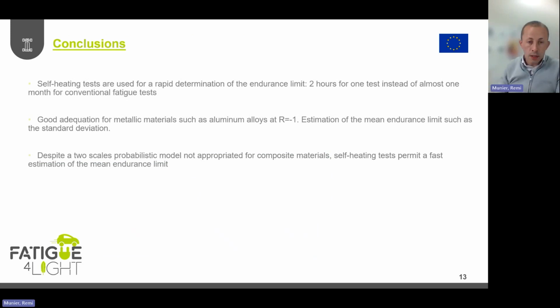And then to conclude, here we can say that self-heating was used for the rapid determination of the endurance limit. One of the biggest advantages of the method is the reduced time in comparison with conventional fatigue tests. As I said before, there can be some mistakes and some limitations, but for bare materials with a homogeneous volume, this approximation is quite good, especially for metallic materials on a wide range of ultimate tensile strengths. There is also a good adequation for aluminum alloys, even at the loading ratio -1.